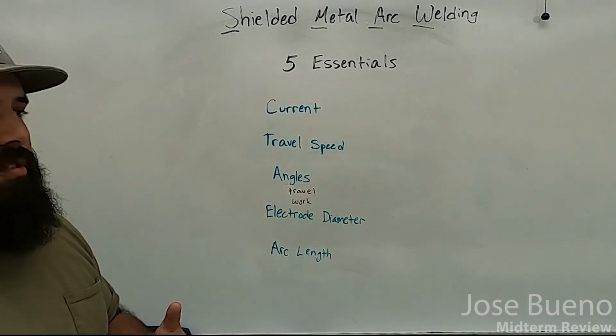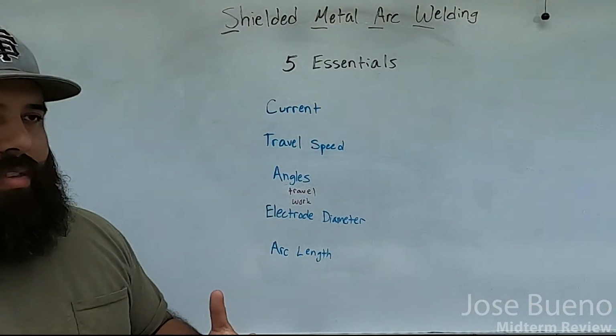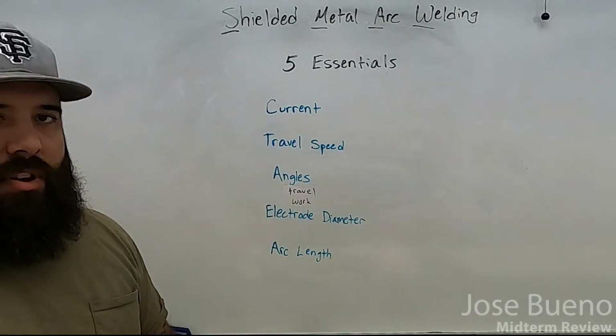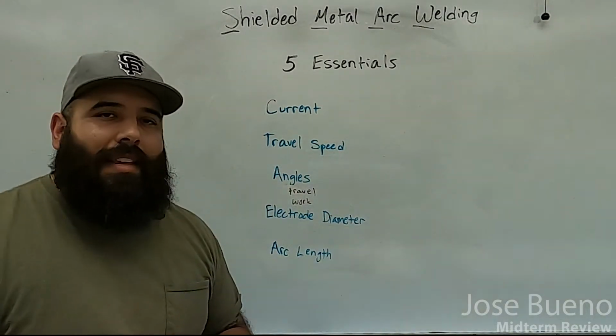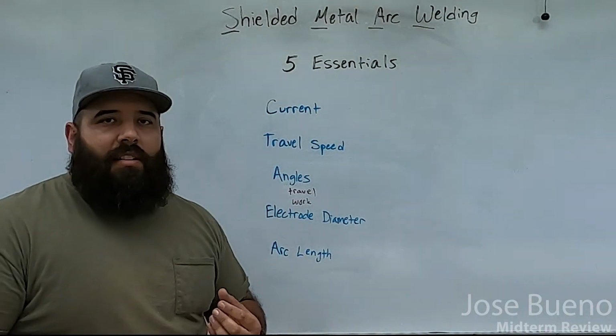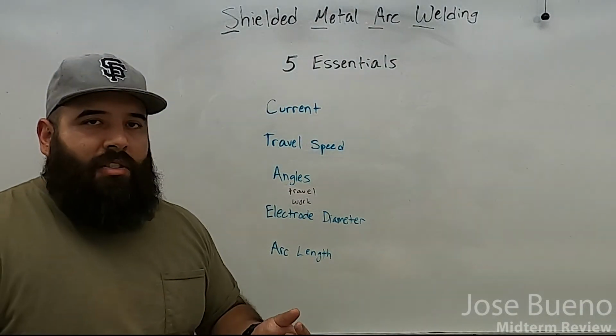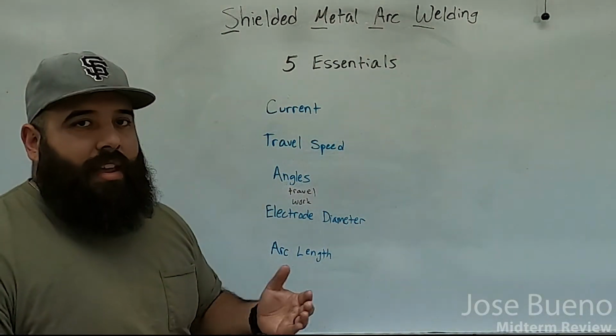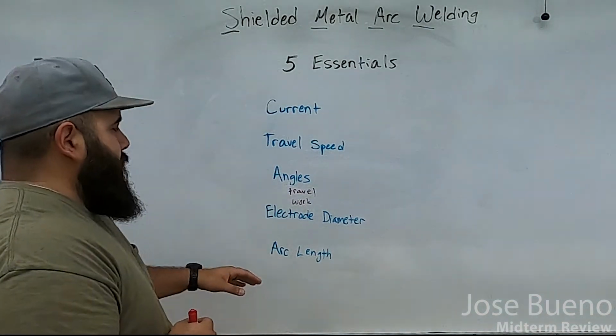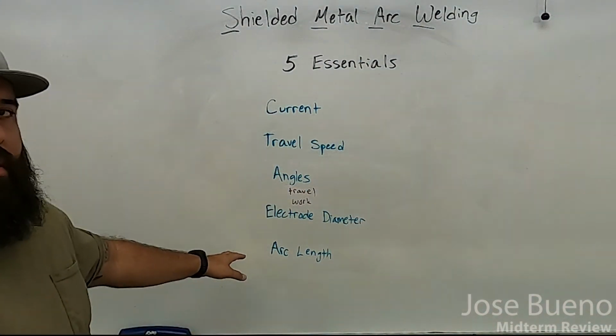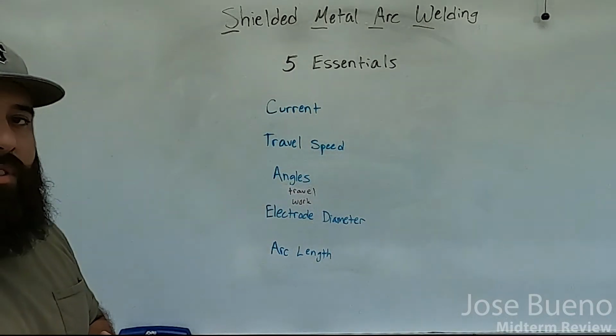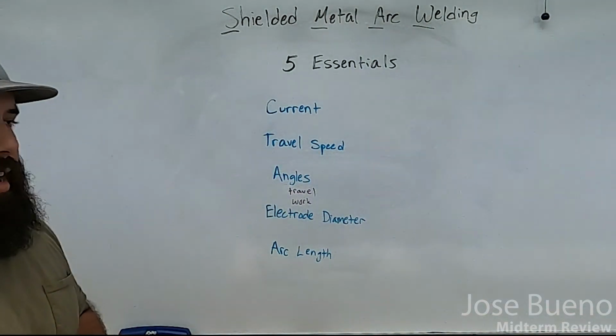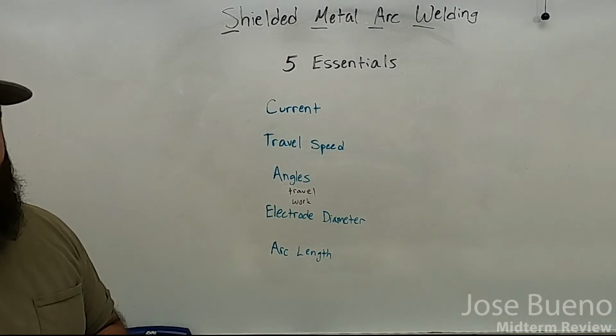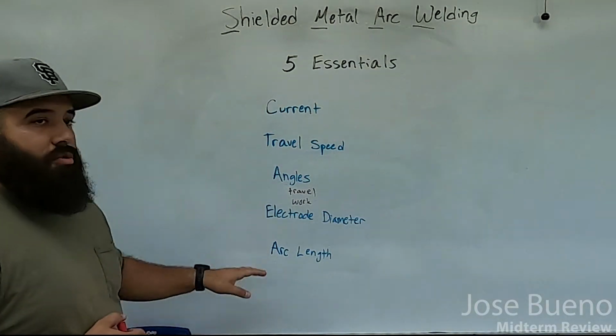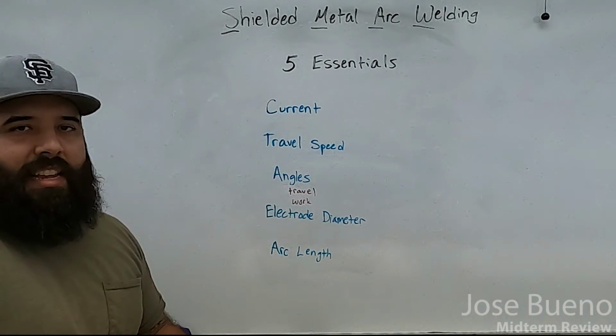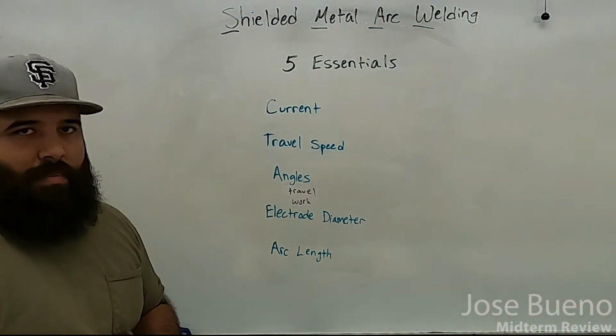So we want to find that sweet spot within one diameter of the electrode. So if you're welding with a 1/8 inch diameter electrode, you want there to be approximately 1/8 of an inch between the tip of the electrode and the weld. As you increase your arc length, you are increasing the resistance to the flow of current. And it's also going to do a couple other things. Just the same where if your arc length is too short, you take a risk of sticking the electrode, but then some other things can happen too.